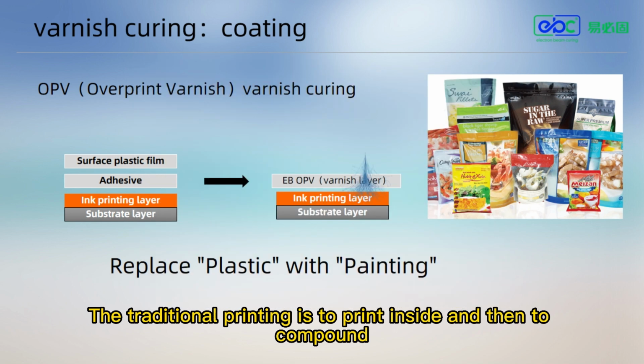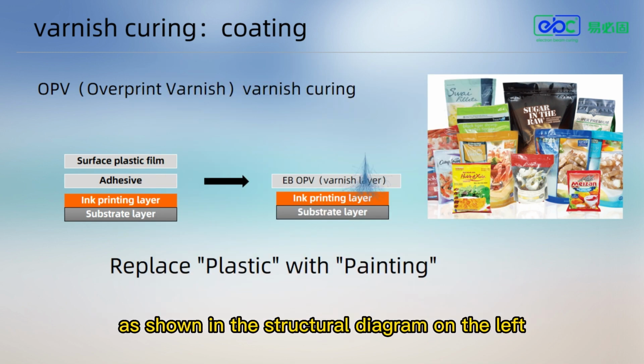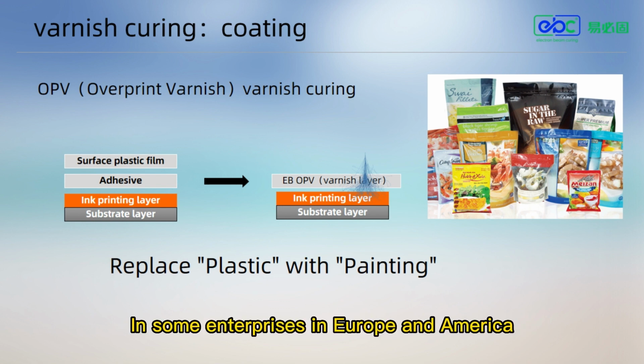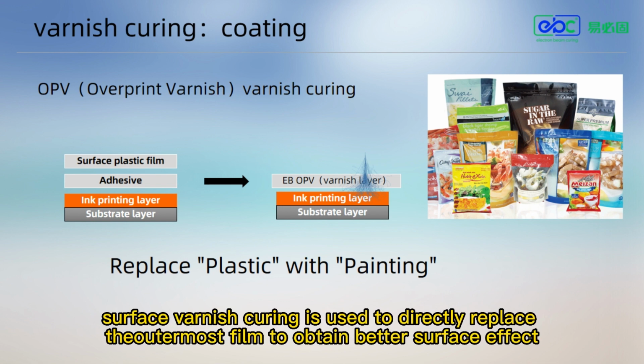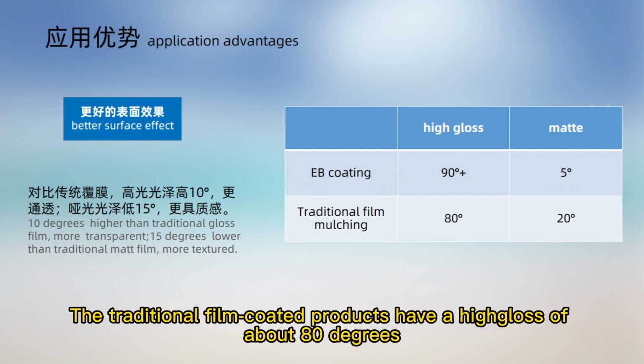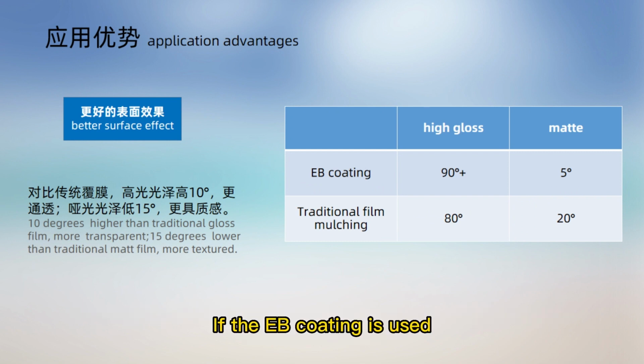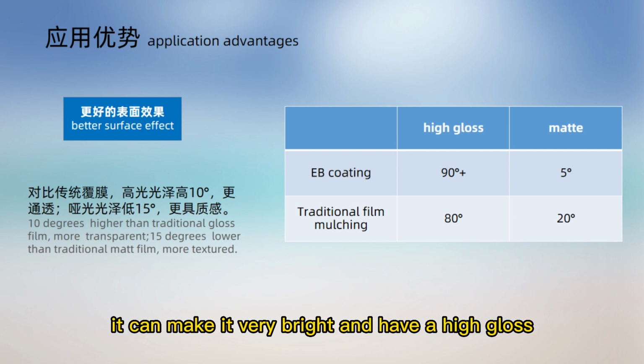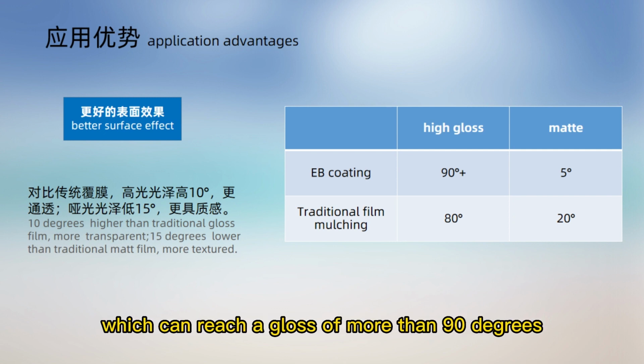The traditional printing is to print inside and then to compound, as shown in the structural diagram on the left. In some enterprises in Europe and America, surface varnish curing is used to directly replace the outermost film to obtain better surface effect. The traditional film-coated products have a high gloss of about 80 degrees. If the EB coating is used, it can make it very bright and have a high gloss, which can reach a gloss of more than 90 degrees.